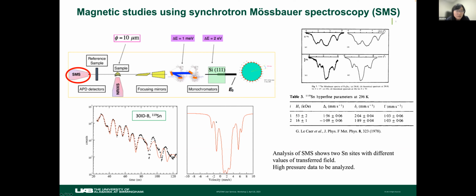on this iron-tin crystal lattice, there should be at least one tin site in the iron-tin layer, and a separate tin honeycomb layer. So just based on this model, we can fit the data reasonably well. This is just a very preliminary analysis. And we compared with the earlier measurements done in the lab using a radioactive source, and the parameters roughly agree. And we have a series of data, and the analysis is in progress.